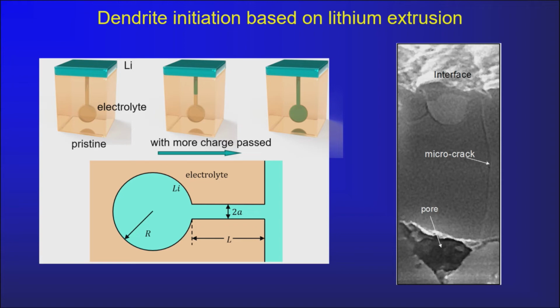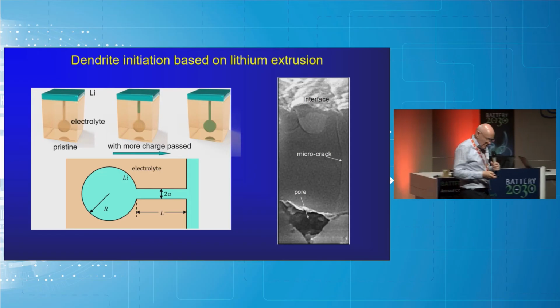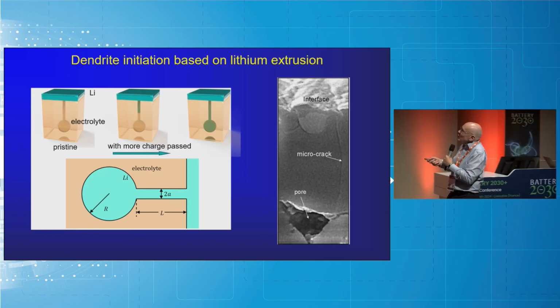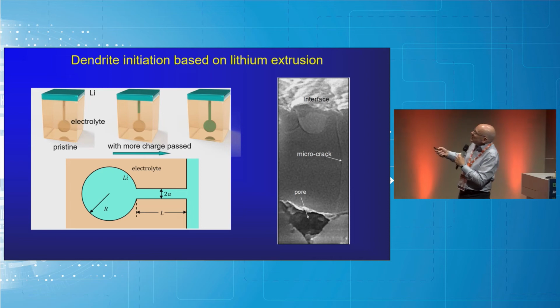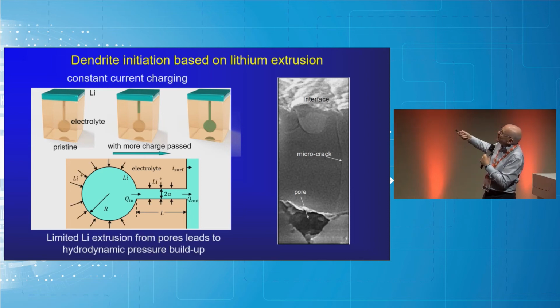So here's the lithium. We're growing lithium. The cylinder represents the crack, and the sphere represents the pore. So you plate lithium here, it passes down this microcrack, starts at the crevice, comes down here, fills the pore, and we end up with this situation where the whole of this space, crack and pore, is filled with lithium. Now this is when the dendrite really gets going, because you're constantly trying to plate lithium at this anode.